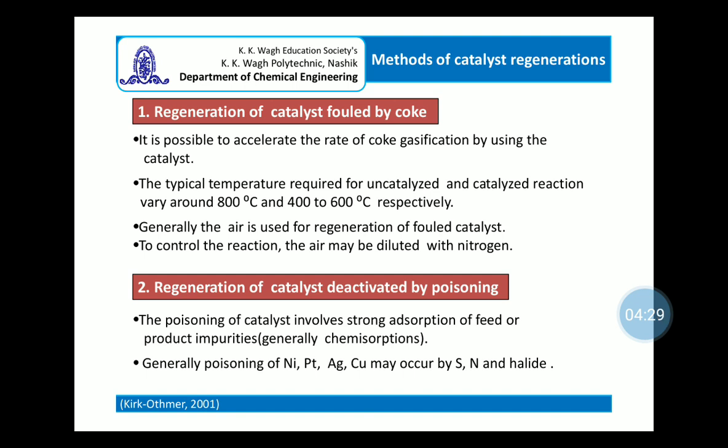Generally, the catalytic reactivation or regeneration processes occur at a lower temperature of 400 to 600 compared to 800 for the uncatalyzed reactions. Generally, air is used for regeneration rather than steam or other gases, and to control the reaction, air should be diluted with nitrogen or another appropriate diluent.